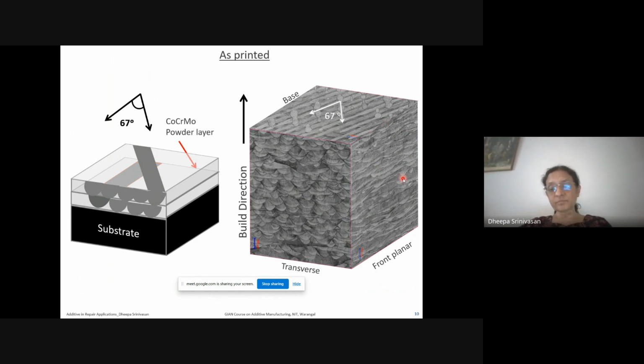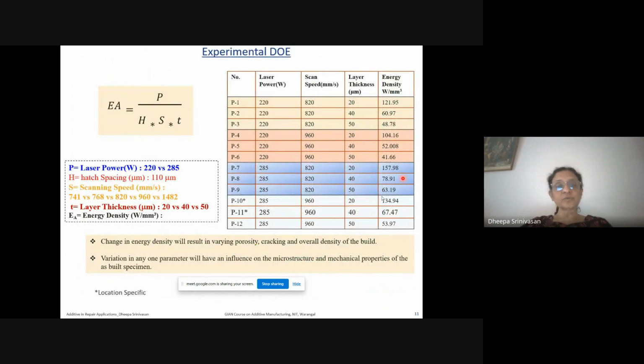However, what I'm going to try and showcase here is a small design of experiments we did during the thesis of Santosh from PSG Tech, where we looked at the effect of the layer energy density in order to be able to get a dense part without any hot isostatic pressing, because most turbine hot section parts, aero engine parts, necessarily need a hipping.